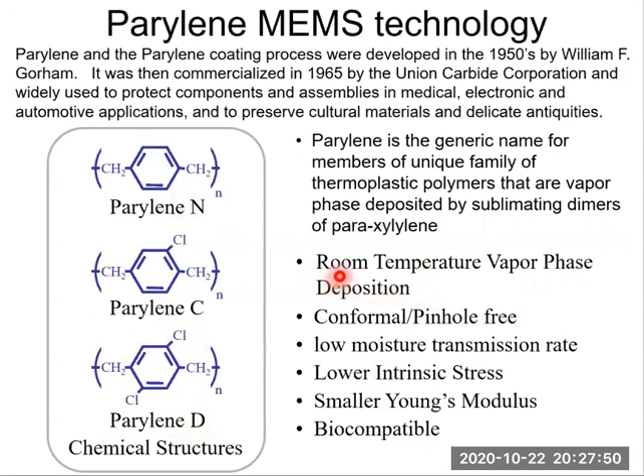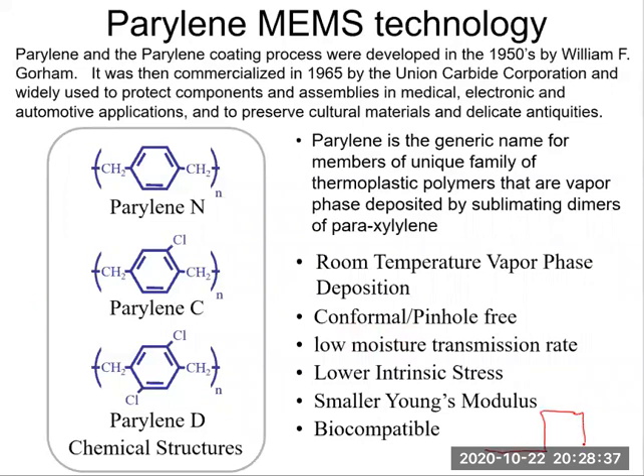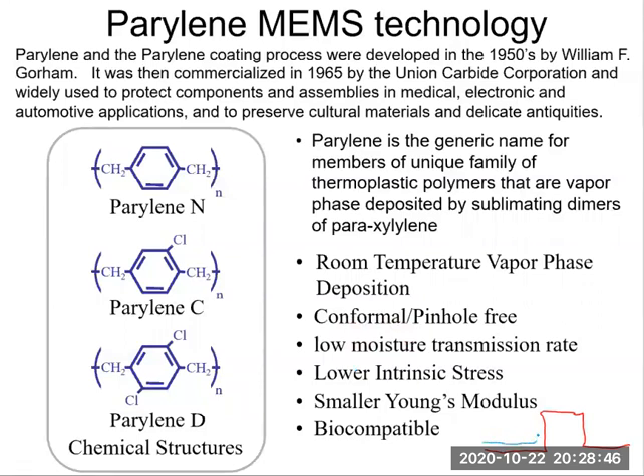Note that parylene deposition is a room temperature vapor phase process, unlike photoresist and polyimide. Photoresist and polyimide are spin coated, and parylene is vapor phase deposited. And this deposition is very conformal and pinhole free. Conformal basically means it has very good step coverage. If we have a step, the parylene will coat uniformly everywhere. We have uniform parylene deposition. Okay, this is a conformal coating.